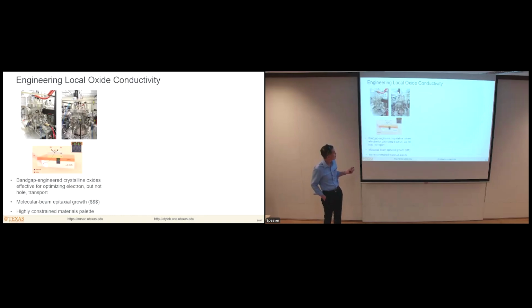Partly because the idea of creating a small band offset works in the conduction band, but it doesn't work in the valence band, because for all these metal oxide materials, the valence bands are very low in energy. So you always have a large valence band offset. It's very hard to get good hole transport. In addition, the deposition technique, molecular beam epitaxy, is great scientifically, but very expensive and not very scalable.